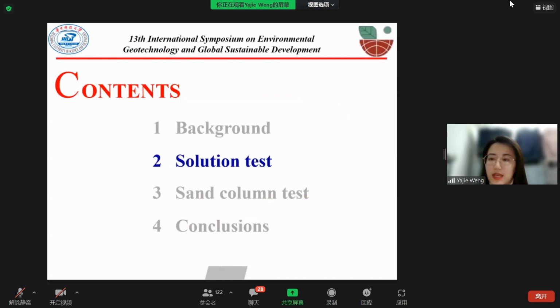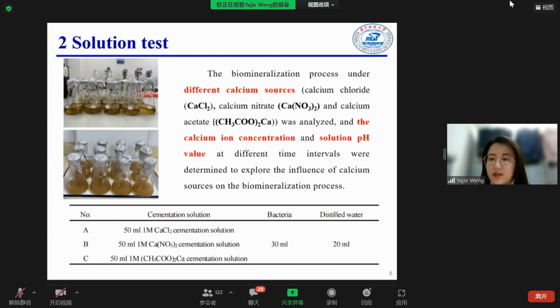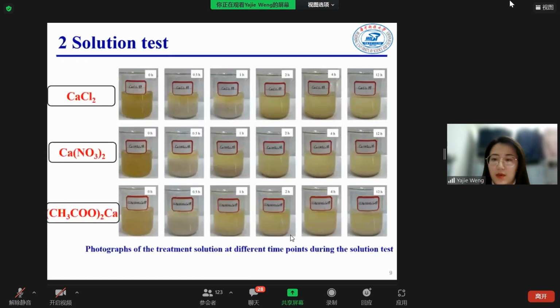The first one is the solution test, whose content is to analyze the biomineralization process under different calcium sources, to determine the calcium ion concentration and the pH value of the solution at different time intervals to explore the influence of calcium sources on the process. The experimental scheme is shown in the table. As we can see from the pictures of the treatment solution at different time points, in the solution test, 3 kinds of solution of calcium salts mixed with bacteria and water produce white flocs, which precipitate at the bottom of the beaker as time went by.